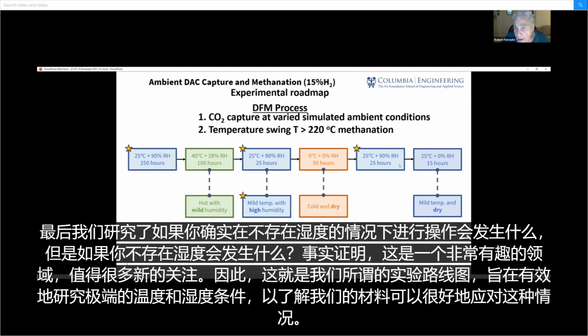And then finally, we looked at what happens if indeed you operate not with humidity present, but what happens if you have no humidity present? And that turns out to be a very interesting area that deserves a lot of new attention. So that's been our so-called experimental roadmap, trying to effectively look at extreme conditions of temperature and humidity in order to see how well our material can manage that.